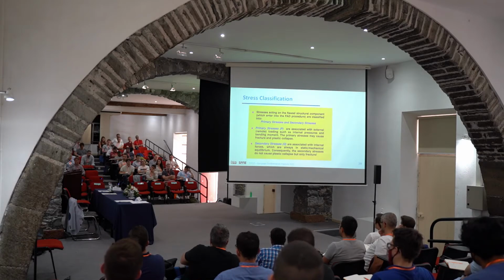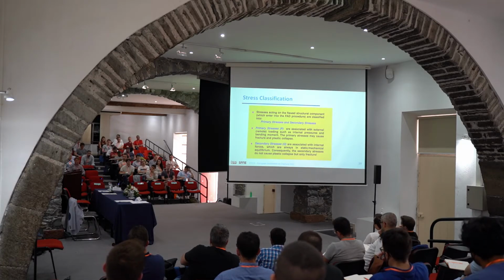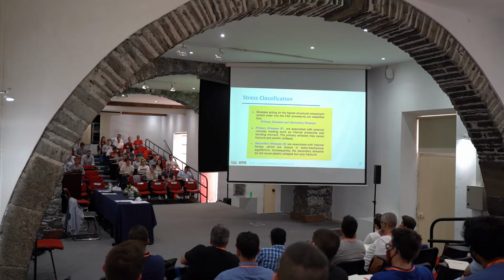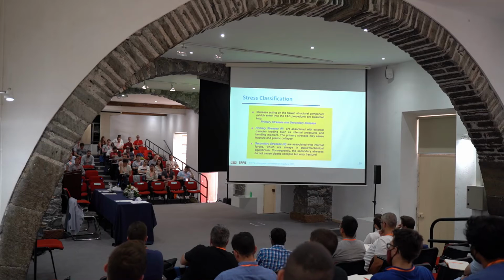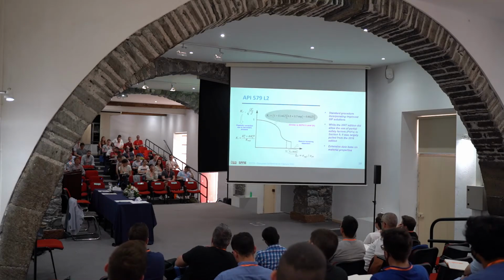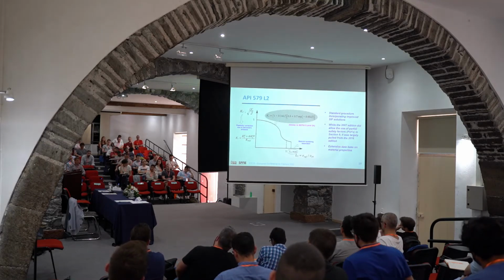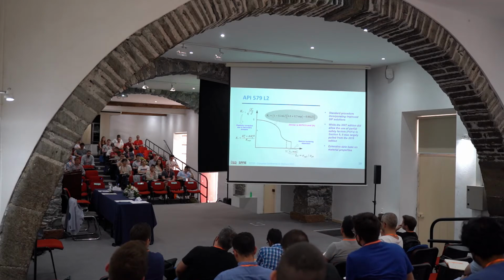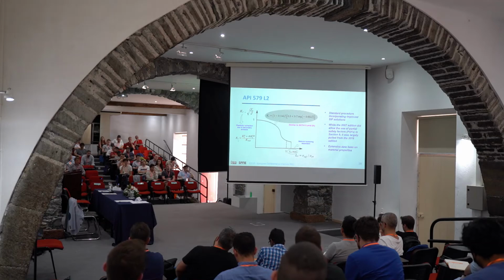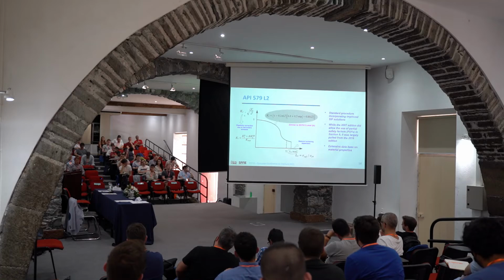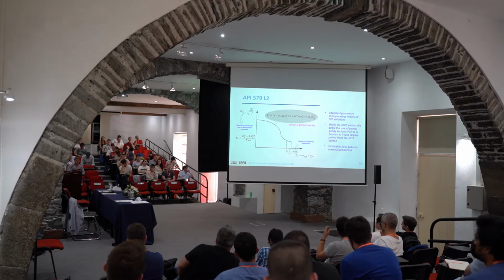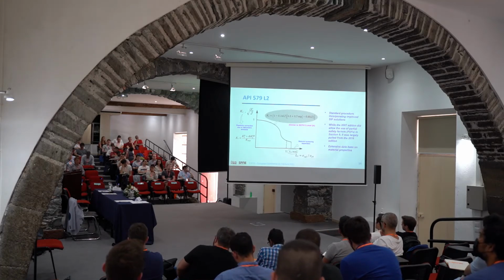And residual stresses are important because residual stresses act on the driving force, on the crack driving force. Okay? So that's why most of the methodologies, they have different ways, but they have a way of correcting the driving force for the residual stress or secondary stress. Okay.